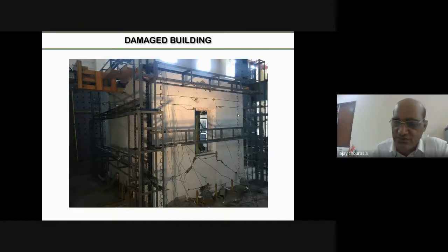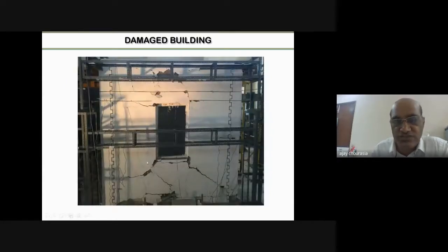While doing so under quasi-static condition, we noted how the damage occurred, and this is the final damage pattern, which is representative of the typical damage pattern we normally observe after an earthquake in masonry buildings. So these are the typical diagonal cracks starting from the opening corners and marching towards the corner, and wider cracks when the displacement is large.